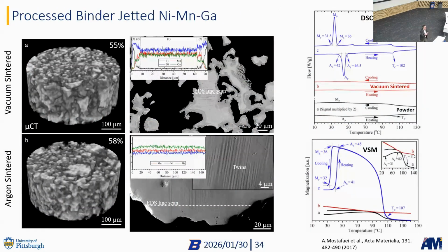And so our first test was what kind of sintering atmosphere actually works with nickel manganese gallium. I worked on single crystals, and when we manufactured them, we had a lot of compositional problems, so I was aware that there can be some issues. We looked at vacuum sintering, and we saw very quickly that vacuum sintering does not work at the surfaces. We have real changes in composition, and those then result in dramatically changed functionality.